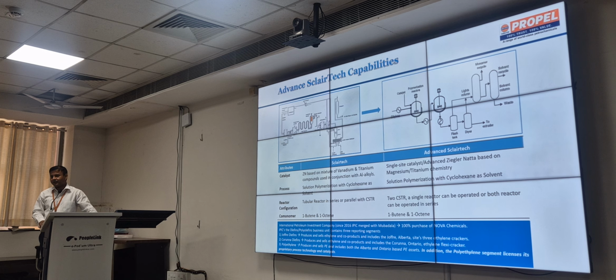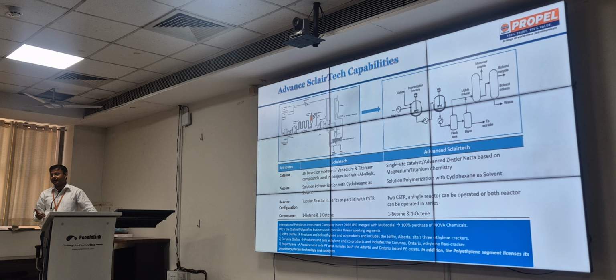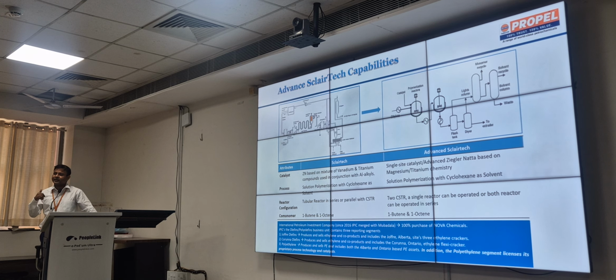Regarding the domestic available capacity, the problem is that we don't have a large number of lines. I have Sclairtech lines, Univation, and HMEL has started with two lines of 400 and 480. We don't have separate lines where we can run dedicated metallocene grades, because when we go for a grade changeover, you have to pay a four-day penalty in production. So that kind of viscous material is produced through metallocene. Players like Exxon, Dow and Borouge have dedicated lines where they can run only the metallocene grades.